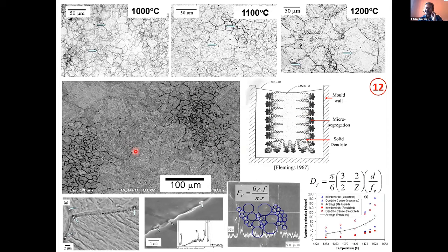So the precipitate fraction or density is less, and those precipitates are also less stable. As a result, when we heat up to this kind of temperature, those precipitates dissolve completely in this region and the grains can grow into large size. So this creates a mixed grain structure. This doesn't happen at lower temperature because precipitates remain more or less everywhere, to some extent. The extent may vary, but precipitates are there everywhere. Even if we heat to a higher temperature, say 1250 or something, then precipitates dissolve mostly from all the locations, and we tend to get a more uniform and coarse grain structure. But in the intermediate temperature range, say 1100 to 1200, we must be very careful, as that can create a mixed grain structure.